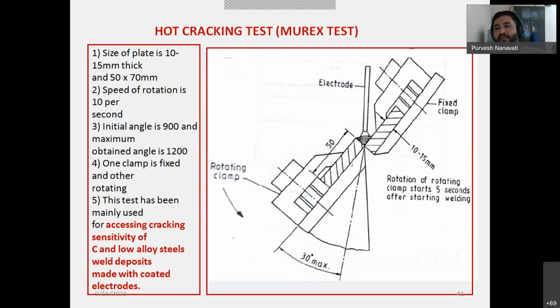Now this test setup is not complicated to understand, but you will see a plate of say 10 to 15 mm thick, and the test plate is 50 to 70 mm in width, right? So what do you see? You see two plates. This is plate number one. This is plate number two.